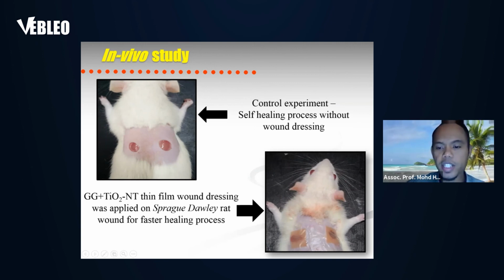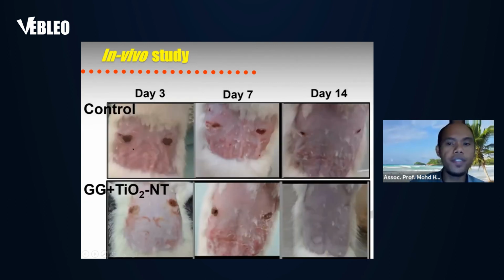So this is when we use our biofilms, titanium dioxide nanotube incorporated in GG, on the wound. This is what we observe in these results on rats. For the control sample, without any biofilm, the rat was left to heal by itself. On day 3, day 7, day 14, we can see that the area of the wound becomes smaller. And interestingly, when we use our biofilm GG incorporating titanium dioxide nanotubes, we can observe that the healing rate is higher.